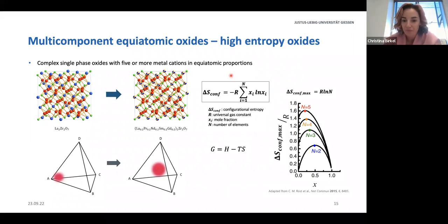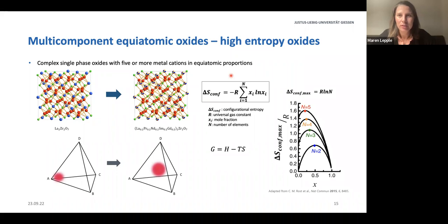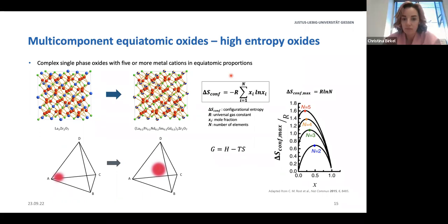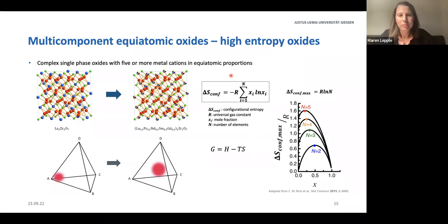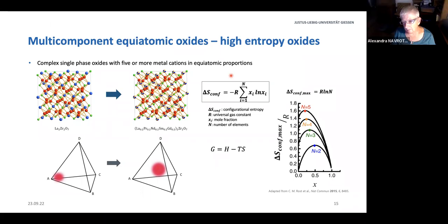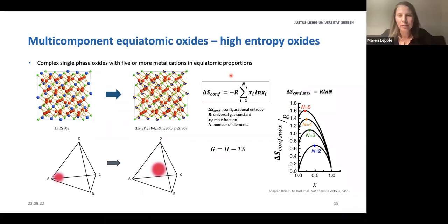Yeah, so we do quite long heat treatments at high temperatures. So for example, 100 hours at 1500 degrees centigrade, to be sure that we reach equilibrium, because we've seen before that, for example, the composition at first looked like it would be single phase fluorite structure, and then after a longer heat treatment, it turned out it was dual phase with the defect fluorite and the pyrochlore structure.